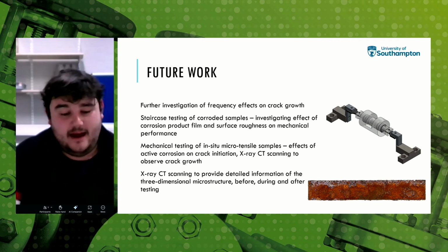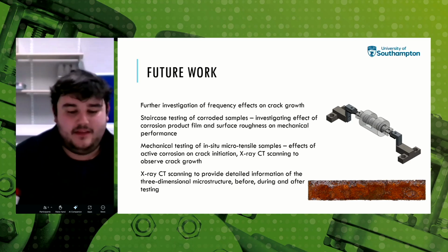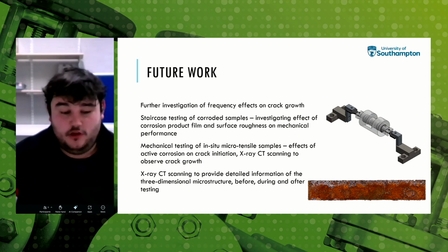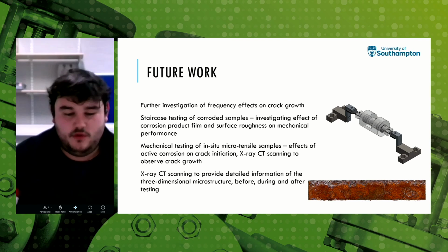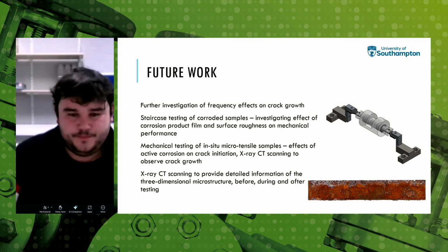Crucially, we'll now be carrying out in situ testing to study the interplay between mechanical loading and the surface chemistry at the same time, while using X-ray CT and X-ray diffraction techniques to look at both the three-dimensional microstructure as well as the changing composition of the product film as the test goes on.